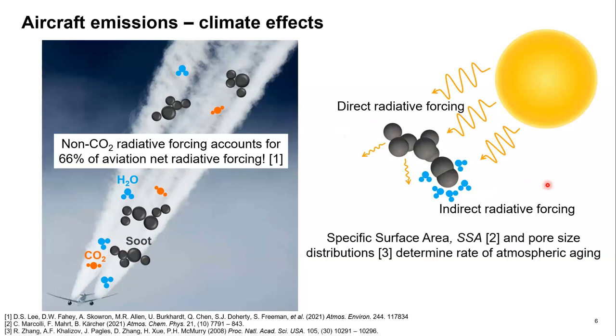Another important component is the specific surface area and pore size distributions of these particles, which determines the rate of atmospheric aging. When the particles are freshly emitted, they have certain properties, but as they age in the atmosphere, this changes. And if the properties change, then their direct and indirect radiative forcing also changes. So it's important to quantify these things in order to understand its impact on the climate.